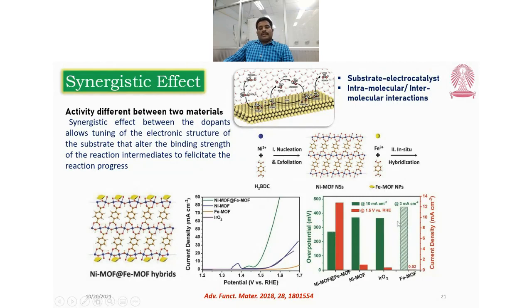The thing is, the Fe MOF alone is electrochemically inactive. When it is mixed with the nickel MOF, it can give better activity. It indicates the synergistic effect between nickel and iron, of intra- and intermolecular interactions.